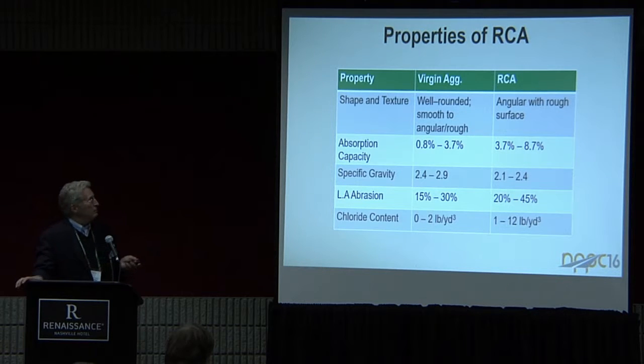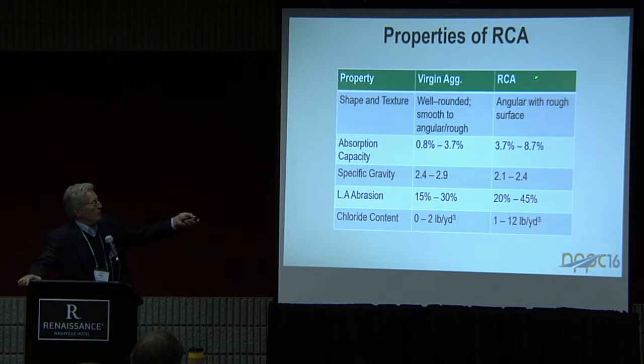Properties of the concrete: again, this is looking at absorption capacity for virgin materials versus recycled materials, and this is assuming you've got recycled crushed concrete, coarse aggregate only we're talking about here. You can look at the numbers yourselves here. Obviously it's going to be a bit higher than you have with natural aggregate because of the fact that the mortar itself has a higher absorption capacity than most of the aggregates do. Since we've got mortar and aggregate together, and mortar has a relatively low specific gravity, we're going to tend to see combined particle specific gravities that are lower than that of natural aggregate as well. Our LA abrasion numbers may tend to be a little higher, but still generally acceptable with most state paving specs for what the LA abrasion numbers need to be.